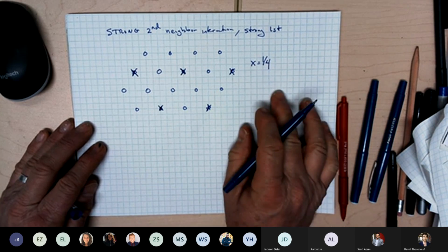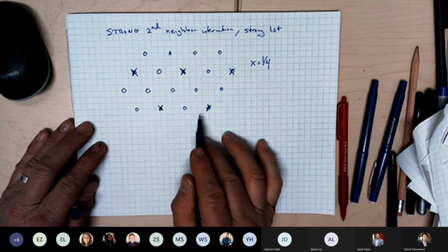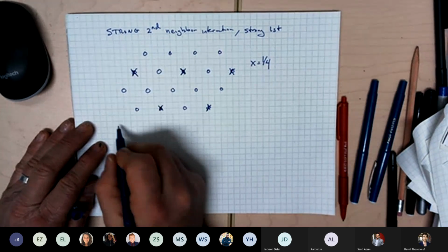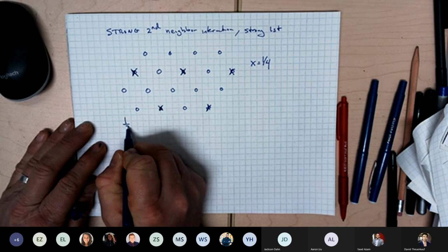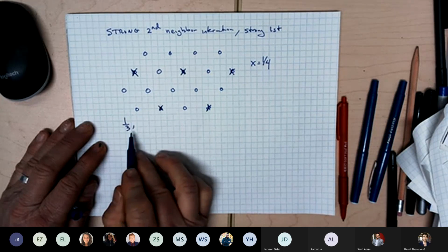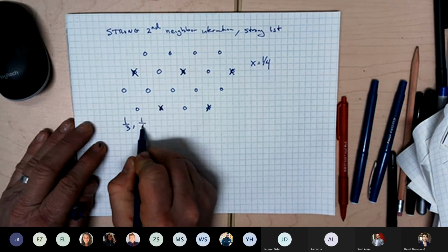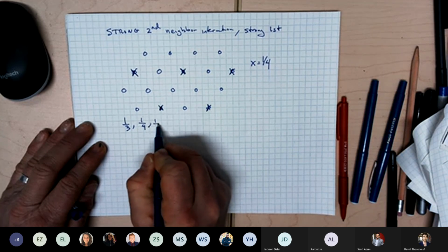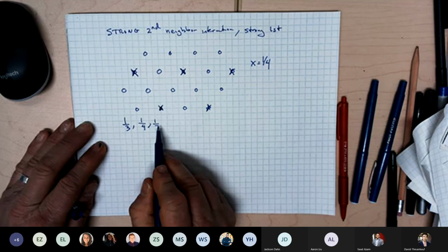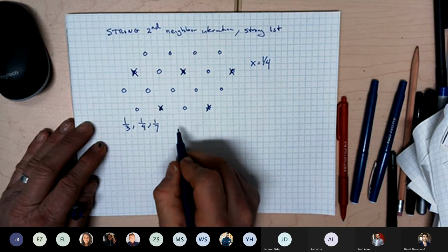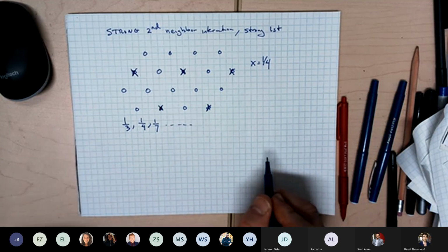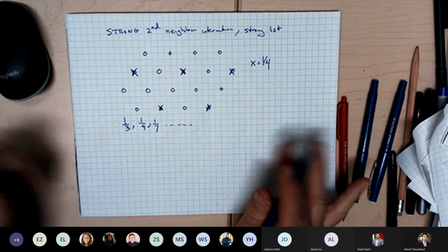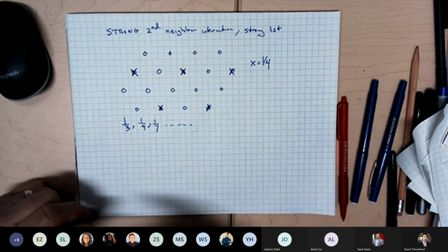So there are all these compositions where the lithium can arrange itself to avoid interactions. And they turn out to be 1/3, which means avoid first neighbor, 1/4, avoid first and second neighbor, 1/7, avoid first, second, and third neighbor, and so on. Okay. So this is what can happen.